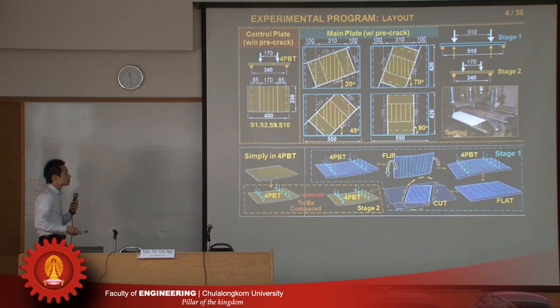So for the experiment, we prepare two types of plate, very thin plate, 2 centimeter thickness. The size is 40 centimeter by 25 centimeter for the standard test, the control plate, we call it. And for the main plate, a little bit bigger one we prepared, but still the thickness is 2 centimeter and the size is like 50 centimeter and so on. Anyway, it's not so big. So to this one, we apply the bending. For the control specimen, we just apply the 4-point bending to check the deformation or multiple cracking and so on.